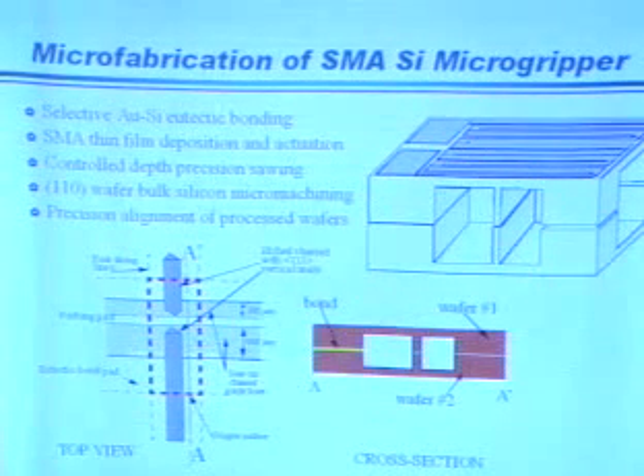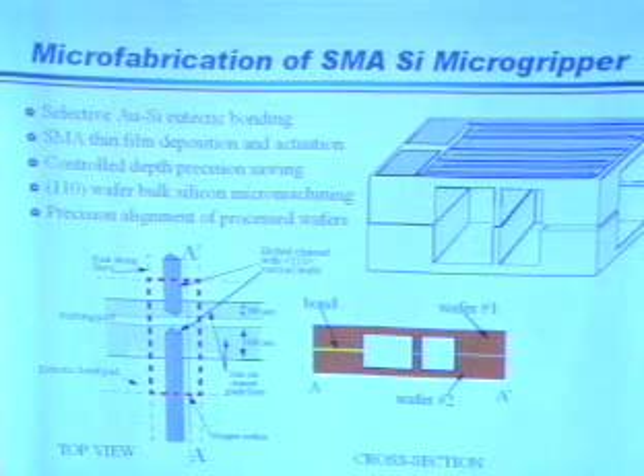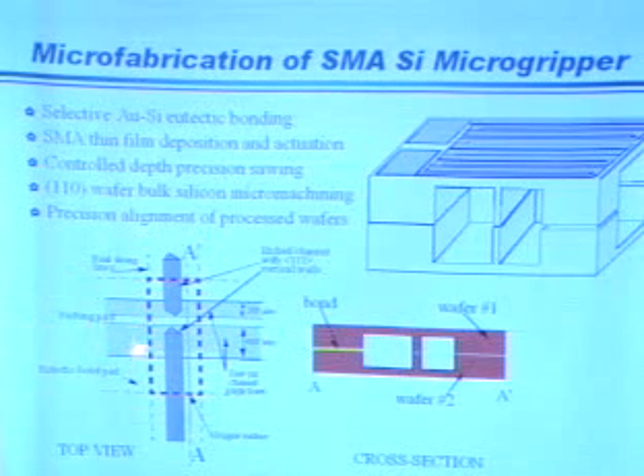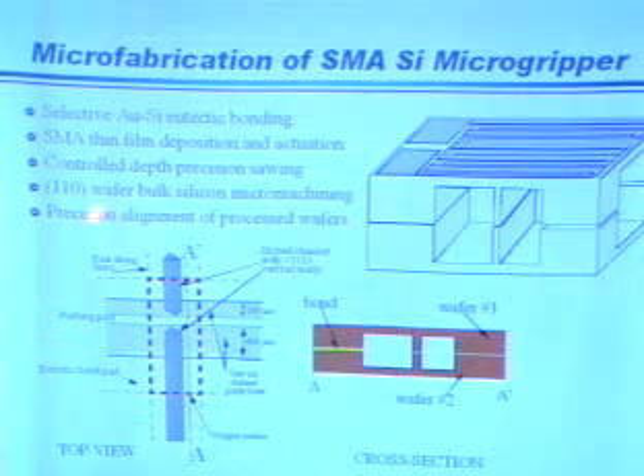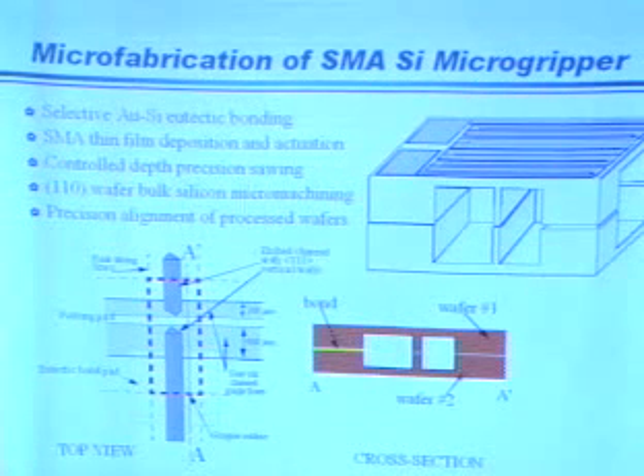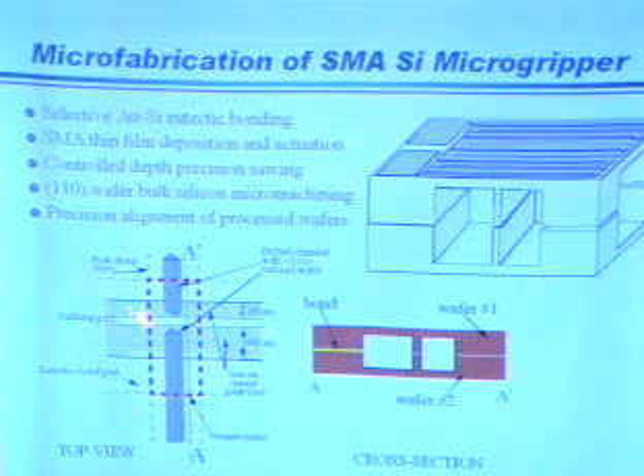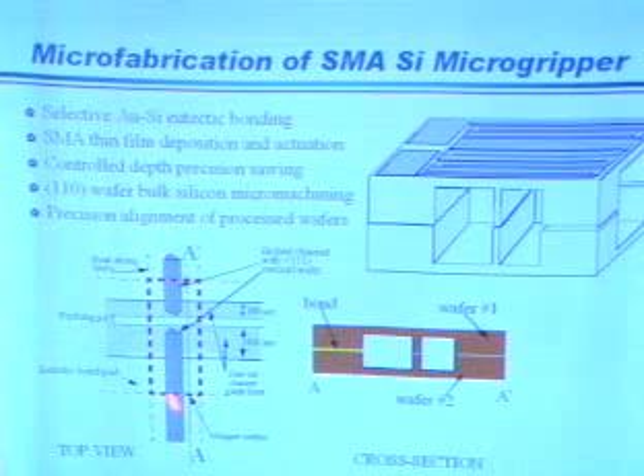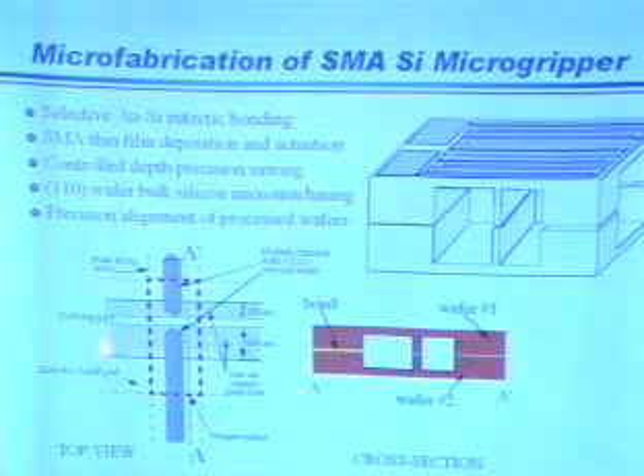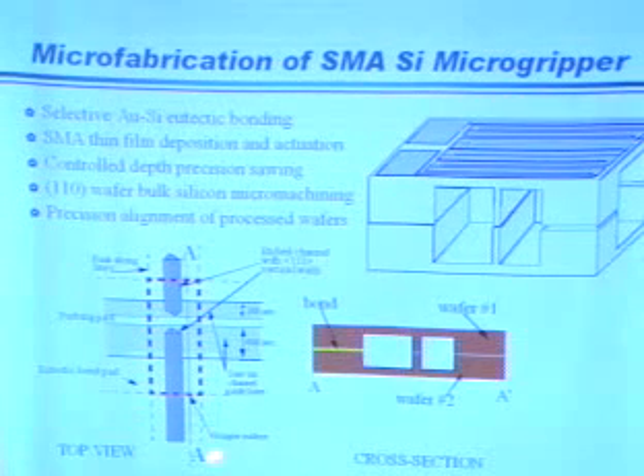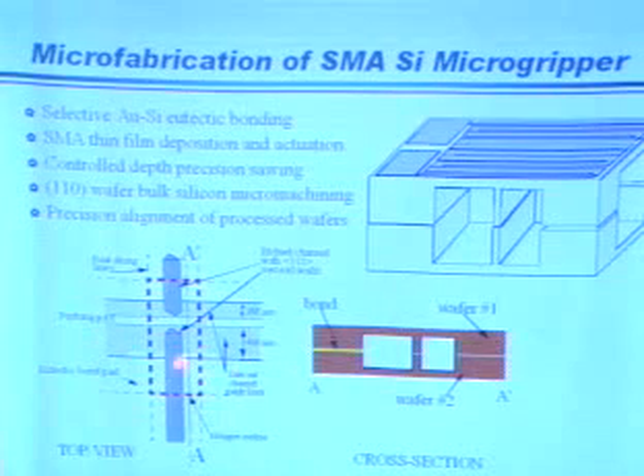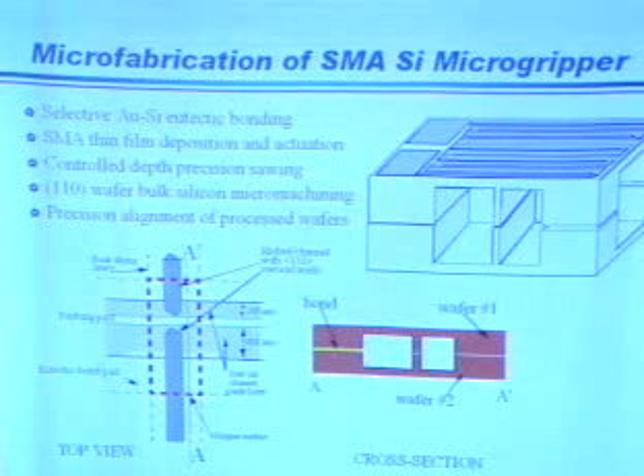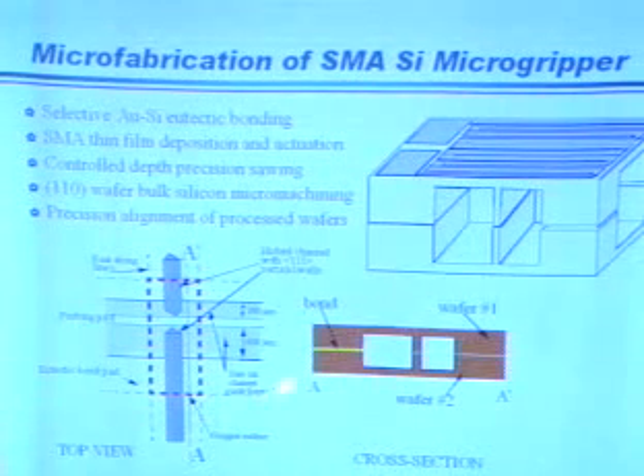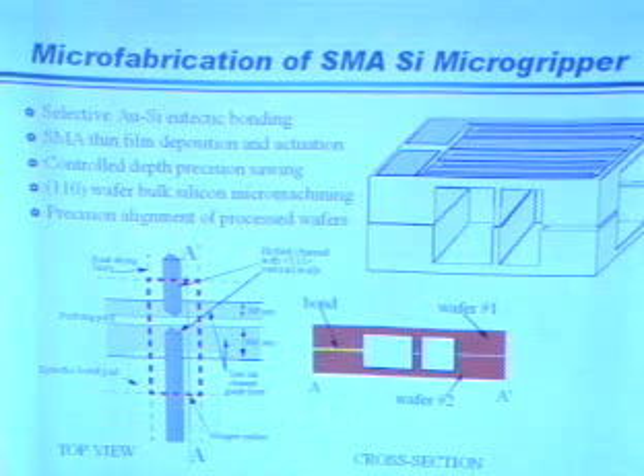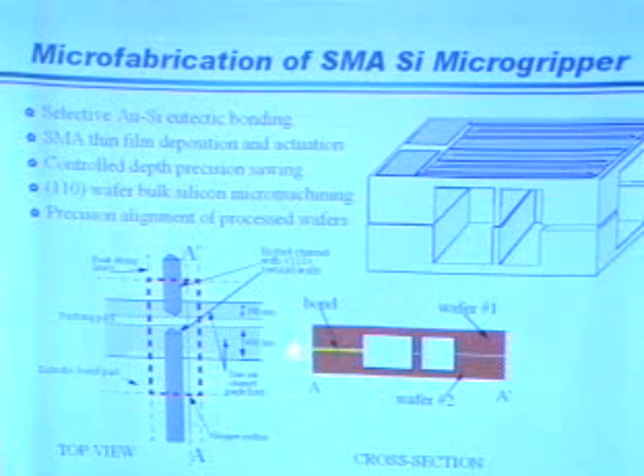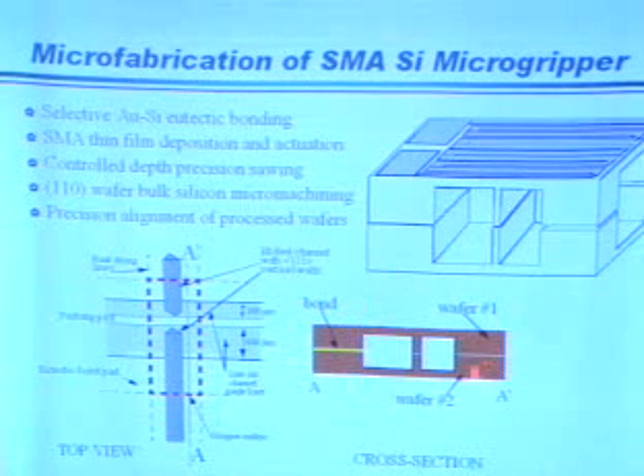So what we ended up doing was etching deep channels with wet etching because of the anisotropic crystalline planes, but we can only etch in one direction with the 110 wafers, and that allows you to have 111 planes in the vertical direction in a certain crystalline plane. So you can etch that. In this case, it's these vertical lines, but you can't etch the other direction. With the other direction, the only way we could figure out was using precision saws, working very hard to get very good control of how deep you saw into the wafer. So this is this direction. The other thing we wanted was a bulk micromachining effect and batch fabrication, so we wanted to make many, many grippers at the same time. And if you want to bond these two wafers together, of course, you need to bond only, for instance, the base portion, so that the other open portion can open up.